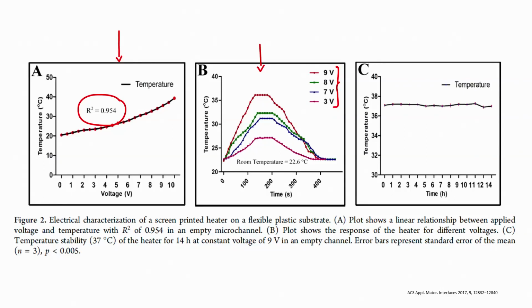Now, whether your heater is stable with respect to time for a particular temperature, that is what your C plot shows: the temperature stability of the heater for 14 hours at a constant voltage of 9 volts in an empty channel. These are error bars here, you can see in the red color, representing standard error of the mean. For n equals 3, we have performed the experiment 3 times, and the p value is less than 0.005. So, we have performed the characterization of the screen printed heater.